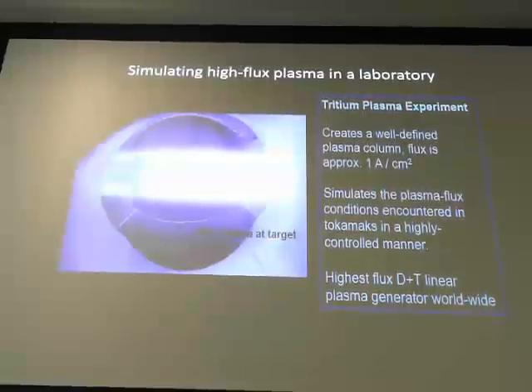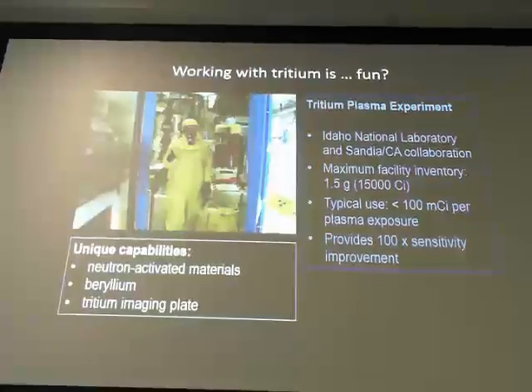This experiment was developed at Sandia and then eventually moved over to INL. It creates a high flux plasma column, about 1 amp per centimeter squared ion current to a surface. And it simulates the plasma flux conditions that you'd expect to encounter in the divertor of one of these tokamaks. It's the highest flux deuterium tritium linear plasma generator worldwide. So it's a unique capability in the sense that it can handle tritium, but because of the same radiation protocols used for tritium, you can also work with other materials, such as neutron activated samples. And so we've had quite a bit of work with neutron damaged materials.